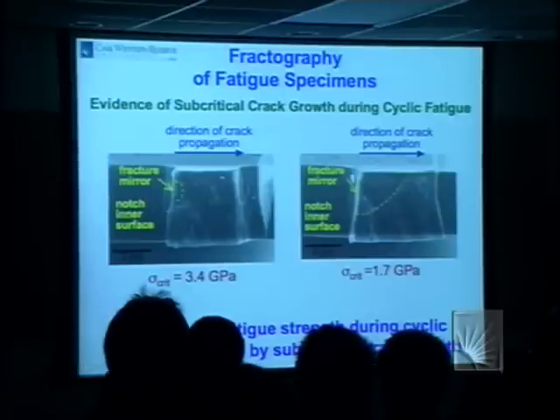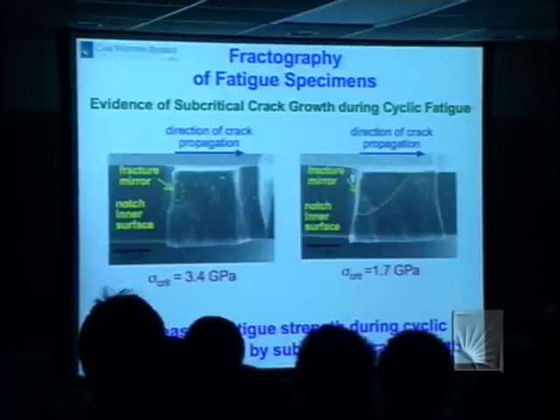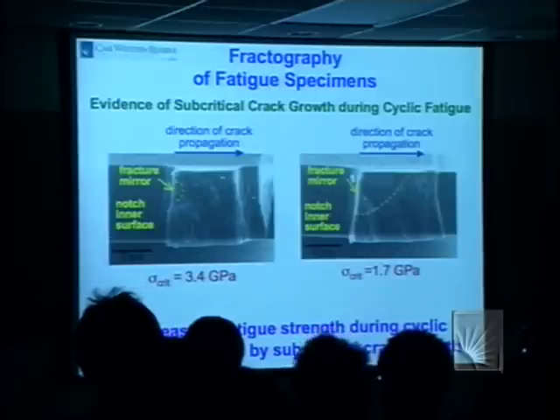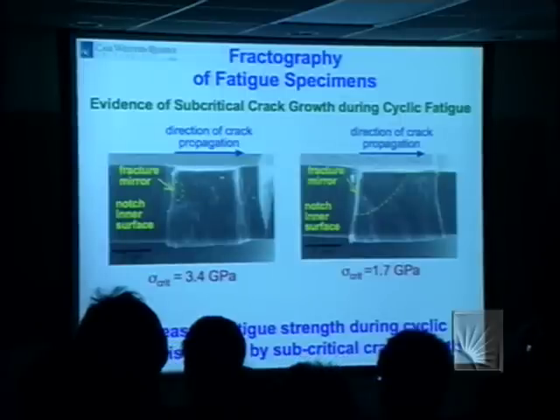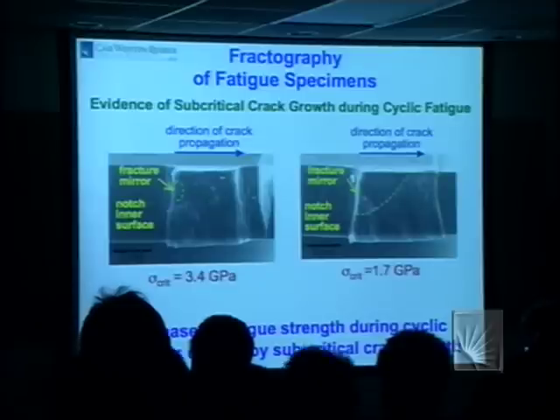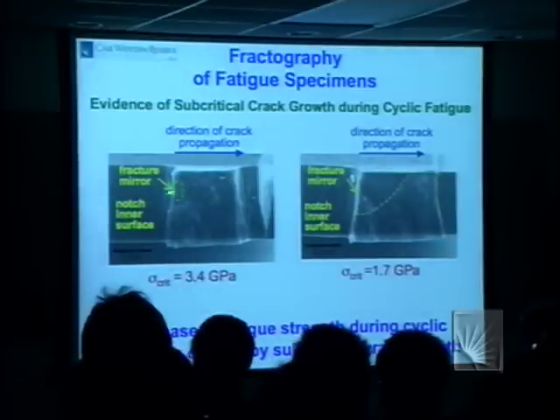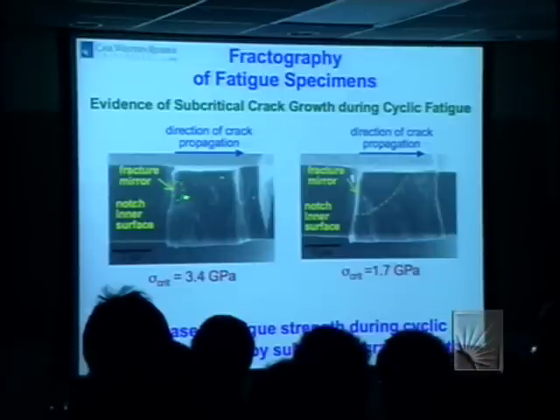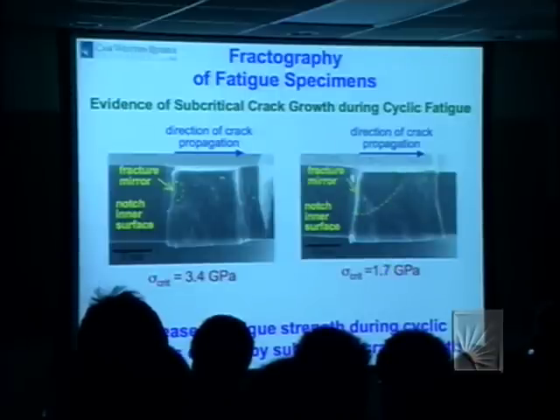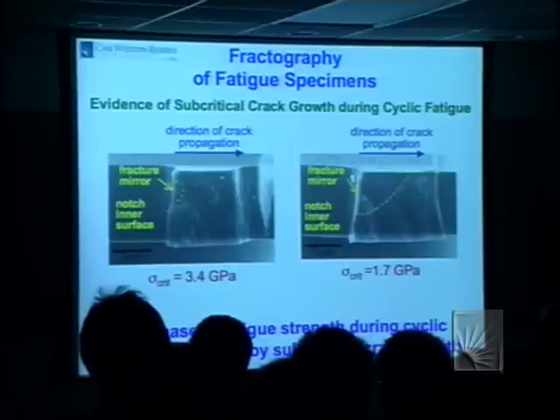And there's a well-established relation between the size of the flaw and the size of the fracture mirror. Essentially, the size of the fracture mirror relates to where the crack velocity gets to the speed of sound. And then the crack is still accelerating, and you get very rough because you get subsidiary fractures ahead of the main fracture. But you can see that at high stresses, there was a much smaller fracture mirror, and therefore a smaller fracture origin, than at lower stresses where there's a larger mirror. And so the implication, very clearly, is that there's some flaw, and it's growing subcritically.